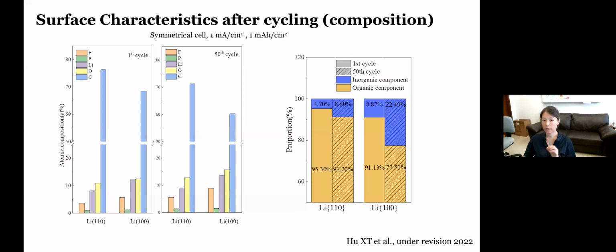They did show that other than the composition of the SEI, the spatial distribution of these compositional elements is also very important in determining the SEI properties, including the ion flux properties as well as the stability with the electrode. But nevertheless, we don't have further characterizations in this regard due to the lack of capacity to carry out these experiments with cryo-FIB and also cryo-TEM. But we're very much looking forward to collaborations with parties who have the capacity to carry out these experiments.